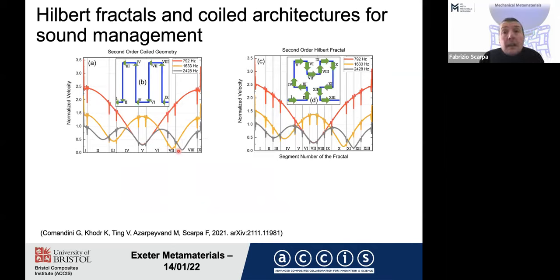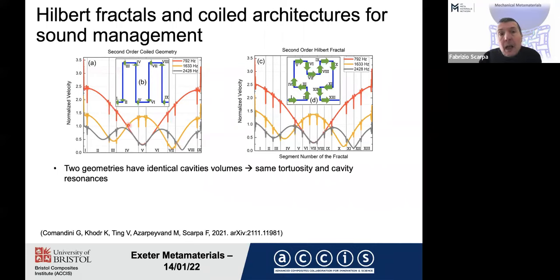Not every cavity resonance inside the air or the fractal will provide you the peak of the absorption. You need to consider those modes that tend to have the maximum difference between the inlet velocity and the velocity in the middle of the fractal. These two configurations, as I mentioned before, have identical cavity volumes, so they have the same tortuosity and cavity resonances. And you can see that the coil geometry and the Hilbert fractal will still provide the same behavior, but the peaks in acoustic absorption only happen when you have this maximum difference between inlet and inside.